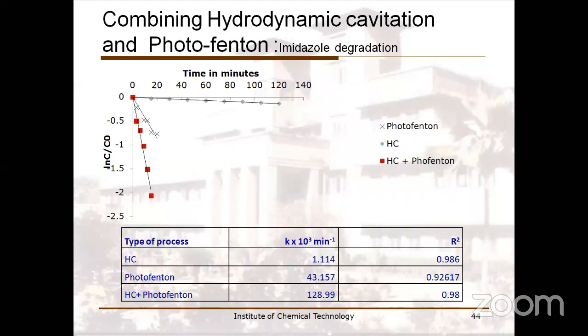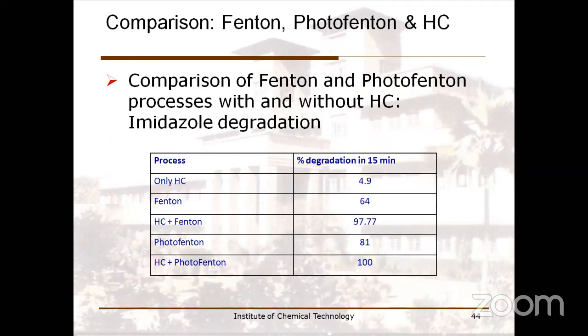You can also combine it with photo-Fenton and then get much better results. So finally you can reach 100% degradation of imidazole. Now the idea here is your combined treatment schemes are working better, but we need to also look at whether all combinations are useful. Because if you combine here, HC plus Fenton is giving you 98% degradation. HC plus photo-Fenton is giving you 100%, so only about 2% increase, but you are putting in additional energy in the form of photo, which means UV light.